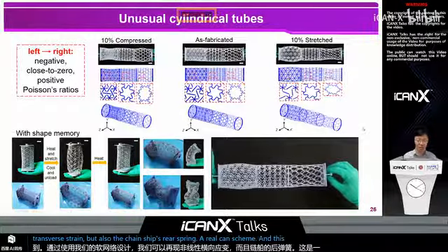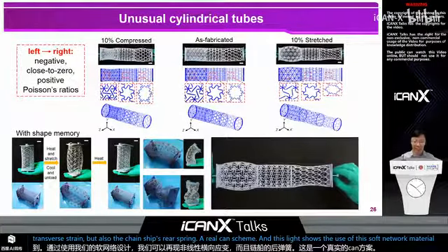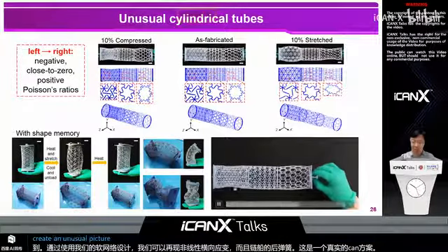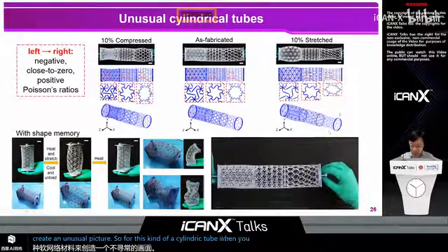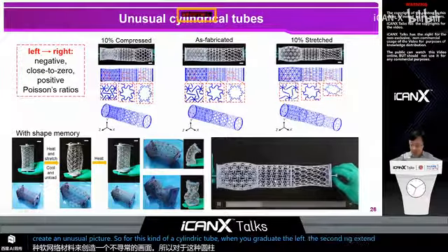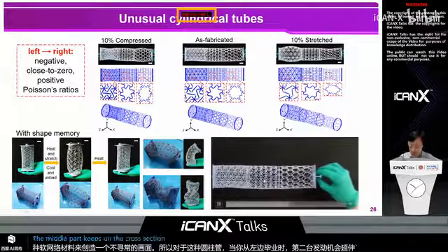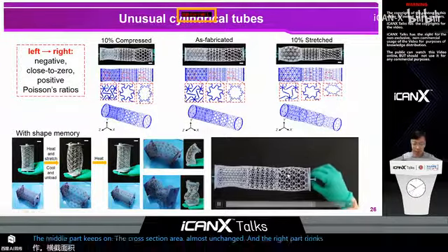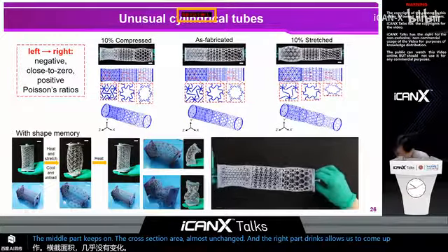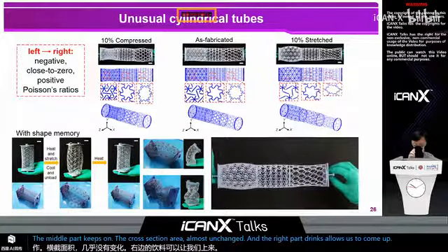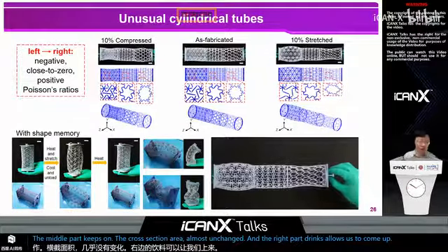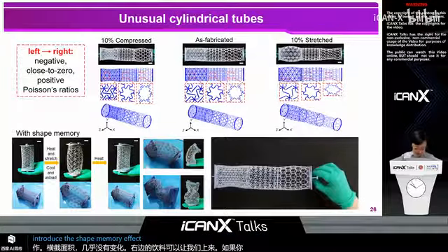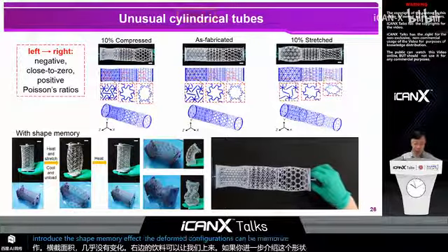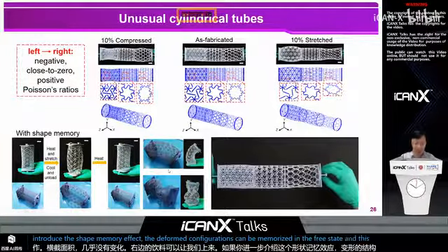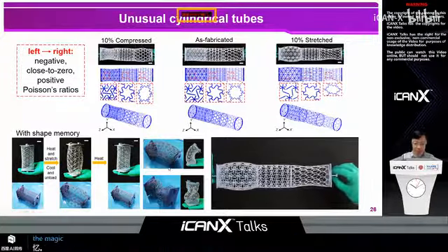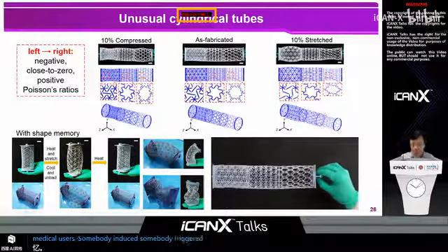And this slide shows the use of this soft network material to create an unusual cylindrical tube. So for this kind of cylindrical tube, when you stretch it, the left segment expands in the cross-section, the middle part keeps the cross-sectional area almost unchanged, and the right part shrinks along the circumference. If you further introduce the shape memory effect, the deformed configurations can be memorized in the freestanding state. And this feature can be utilized in thermally triggered medical stents.